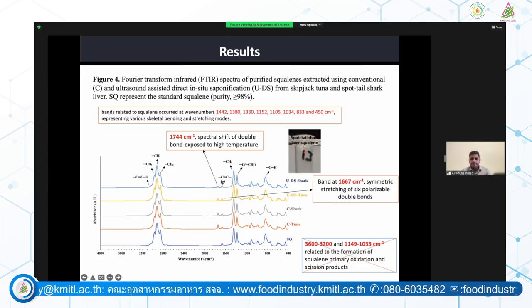And next, we can see there is a thermal shift. Thermal shift is nothing but the oxidation due to the higher temperature of extraction. As we can see, this is the conventional extraction method, and there is a thermal shift. There is a higher change in the structure of squalene when we extract with the help of temperature. When we extract with the help of ultrasound at lower temperature, there was less thermal shift of the squalene structure, so the structure would remain intact. And the absence of peaks in this region specified that there were no primary oxidation products of squalene.